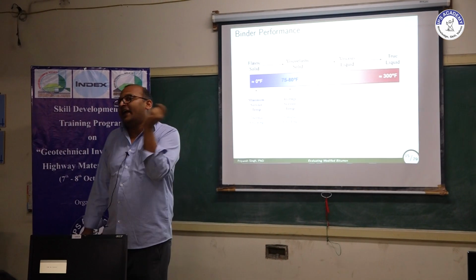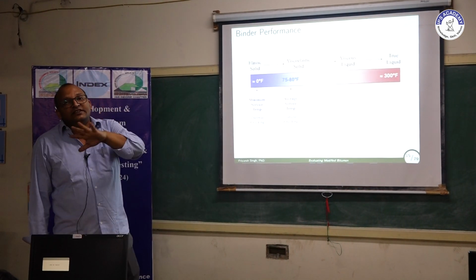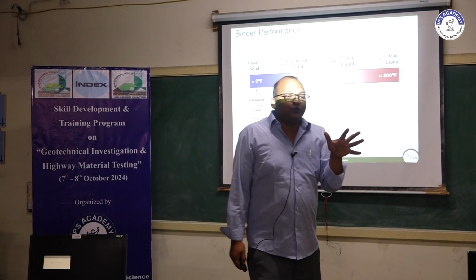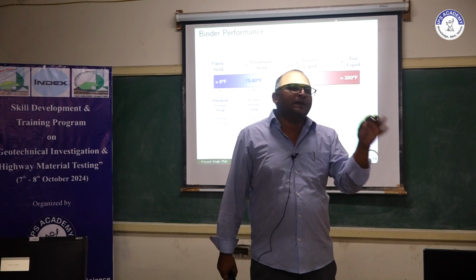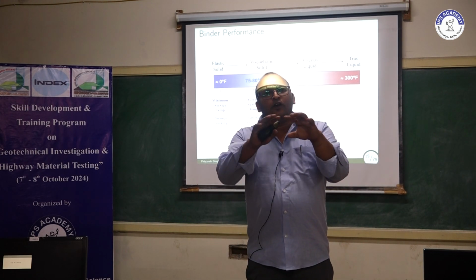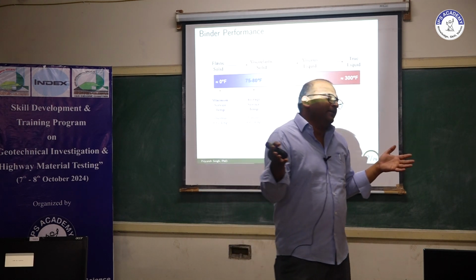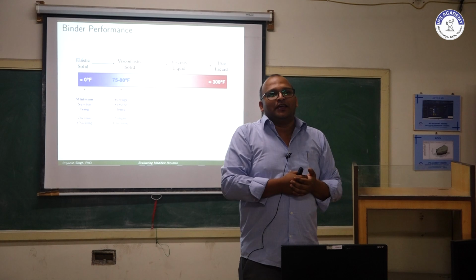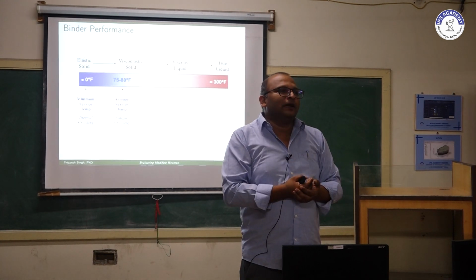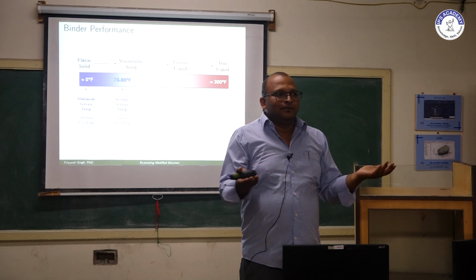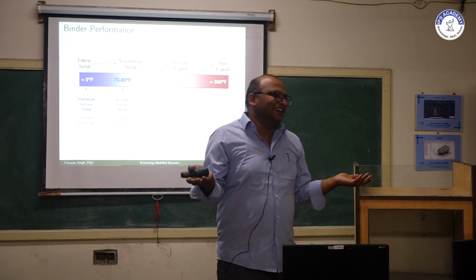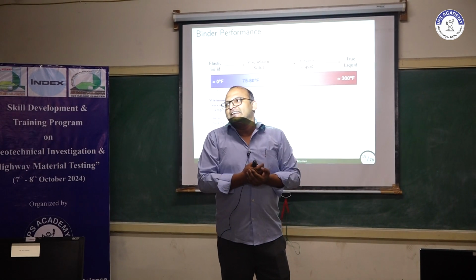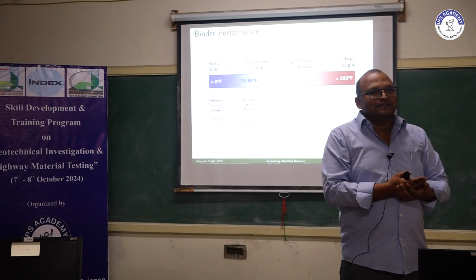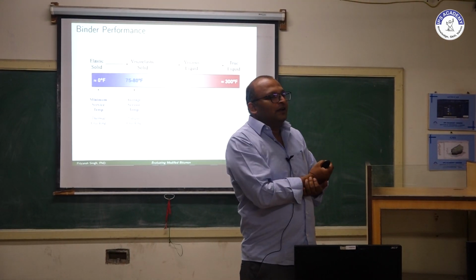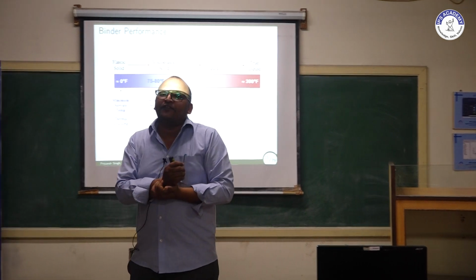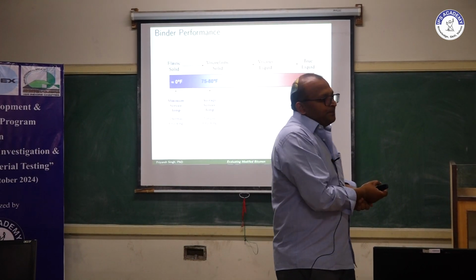The next temperature that is important for the binder is the average service temperature. That is around 25 degrees Celsius. Now this 25 degrees Celsius temperature is very important. If you want to connect this 25 degrees Celsius temperature with whatever tests you have performed today: at what temperature you have done your penetration test? At 25 degrees Celsius, isn't it? And at what temperature you have done your ductility test? 27. That is as per the old code. Now it is being revised. We need to do the ductility test at 25 degrees Celsius on the RTFO aged sample.